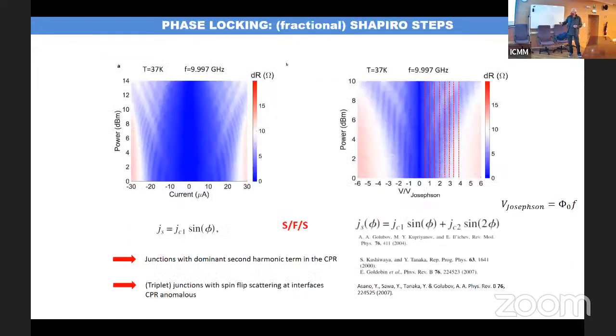So we have measured this, and these are maps of differential resistance as a function of current for different powers of the microwave radiation at 10 gigahertz. And we get, I mean, there's no question, one characteristic interference process. And when we plot these maps as a function of voltage, we get very clear Shapiro steps. But interestingly, these steps occur not at integer values of the ratios of the voltage over the Josephson voltage, but half integer. I mean, there is a doubling. This is the doubling of the periodicity, right? And doubling of the periodicity means that there is a dominating second harmonic in the current phase relation.